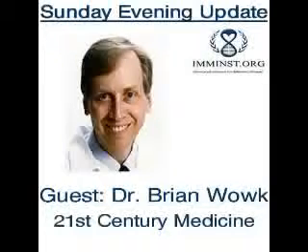So basically what seems to happen is once you cross a threshold of around 40 or 50% replacement of water around proteins and possibly other biomolecules, something happens that affects their ability to recover their normal function when the cryoprotectants are removed. And we don't know whether it's protein denaturation or something more subtle, but there's some problem that's related to replacing so much water in biological systems.